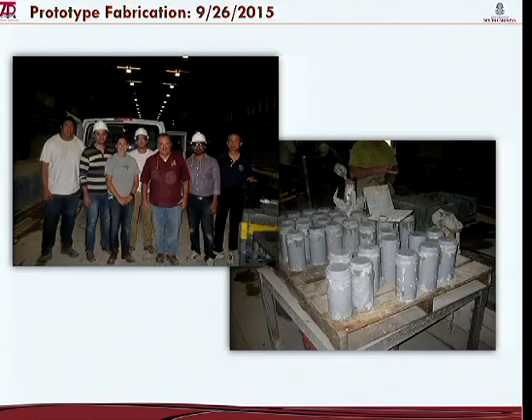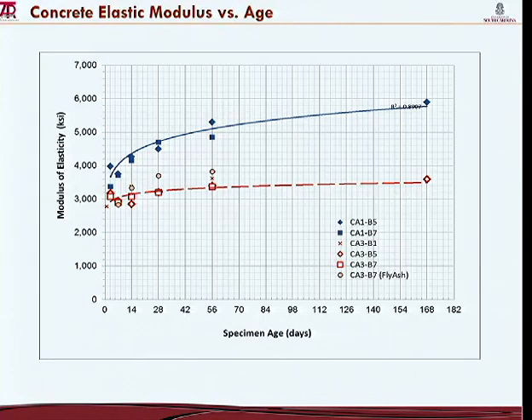This is the team with my students. I'm very proud of their work. And to put this in graph form again, we look at the modulus of elasticity versus age. We go to about 6 months now. And the trend continues. Concrete produced a third time, under completely different conditions, not by us. And this is the concrete with the weathered aggregates. And in these numbers, we also have included one of the batches from our lab testing just to make sure that we are in the same range of values.